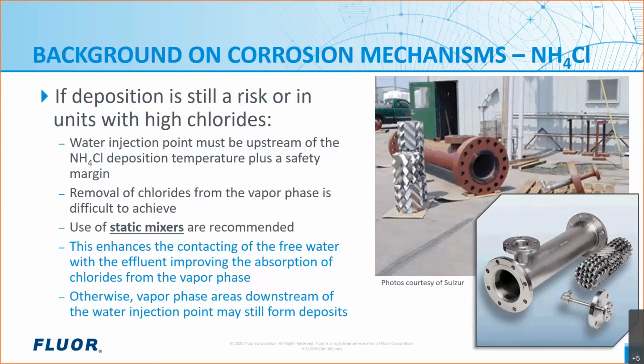So now we've seen a number of units, and Fluor's done a bunch now, where we have the static mixer right after the water injection point. The static mixer enhances the contacting of the free water with the effluent, improving the absorption of chlorides from the vapor phase. Otherwise, even downstream of the water wash, any place there's a vapor phase, like stratified flow in horizontal piping, in the REAC tubes that might be stratified flow, that vapor phase still would have a risk of forming ammonium chloride deposits if you don't strip the chlorides fully out of the vapor. So static mixers are one of the latest and greatest practices that we want to highlight in this talk.